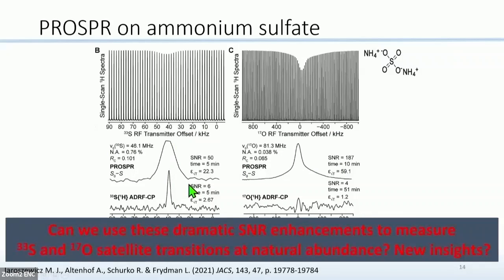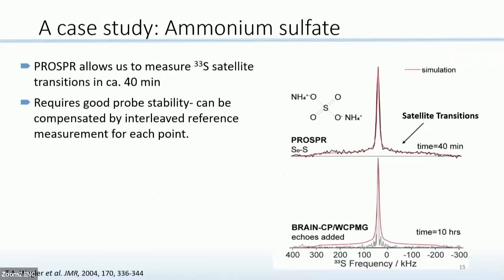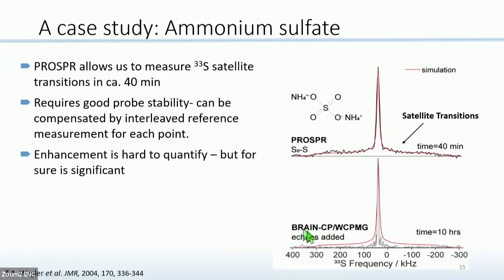We saw here that we got relatively narrow satellite transitions. And we were wondering, can we use these dramatic SNR gains to measure the satellite transitions at natural abundance, and perhaps gain some new insights by doing this? So we started by measuring sulfur. Above here we see the sulfur measurement, and below the compared optimized BRAIN-CP/WCPMG, and we saw that we indeed could measure the satellite transitions in only 40 minutes.